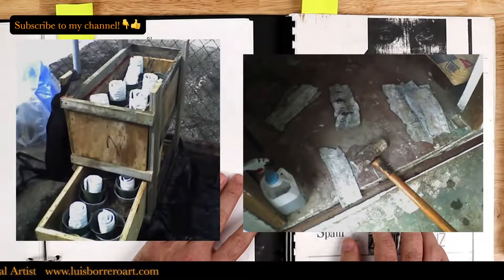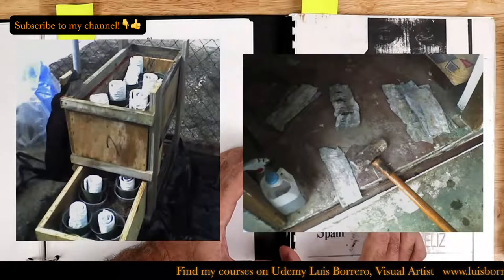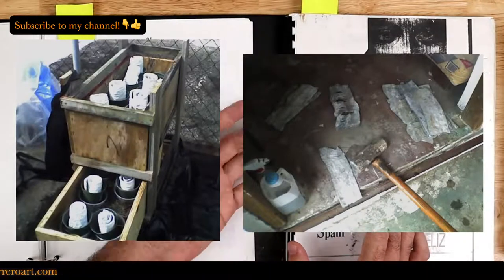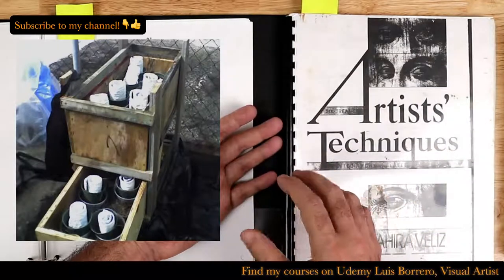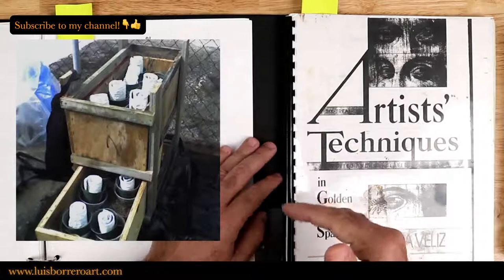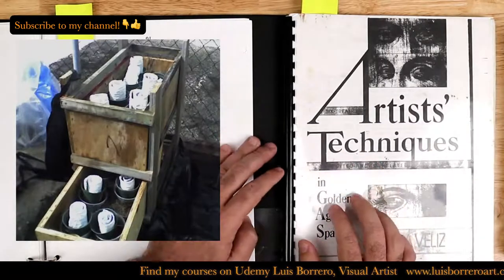Once I've done this, I will roll these pipes, and I will put them in. This is the actual stack. This is an actual pot, little pots filled with vinegar. Now, these are not clay pots. They're just regular plastic garden pots. I'll use a double pot, a pot that is sealed on the bottom with vinegar, and then a second pot inside of that pot with the actual coil. And what results after 3 months, 90 days to be exact, is you see here the actual coils, the lead coils have oxidized, and you get there the basic lead carbonate.